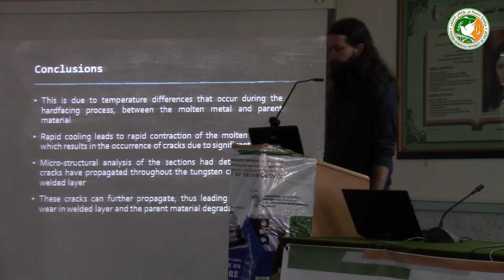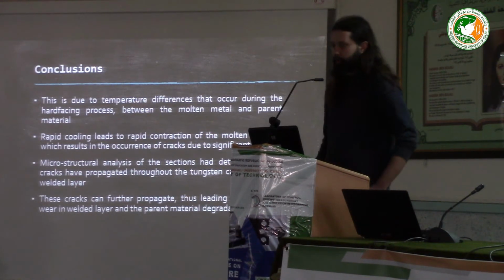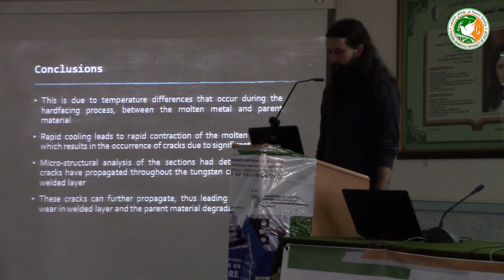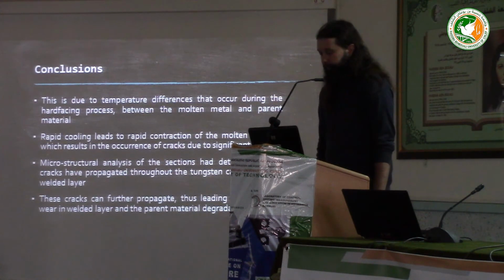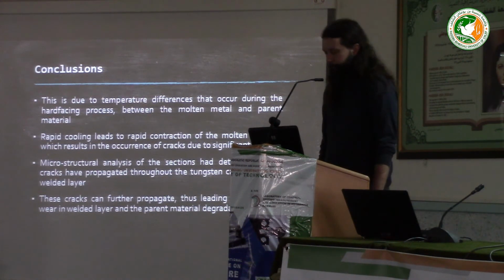This, of course, is the result of temperature differences that occur during the hard-facing process, because the materials melt and then, due to rapid cooling, they contract quickly, which results in considerable strain levels, which in turn cause cracks to appear.